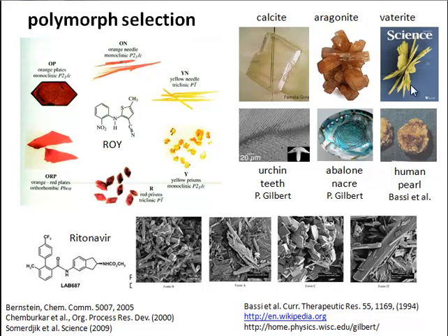These all have the same chemical composition, the same calcium carbonate structure at the molecular level, but it's packed differently into the crystal structures, and it gives you very different crystal morphologies and very different physical properties. Different organisms have learned to use these for different parts of their skeletons for all practical purposes. This one, by the way, is a human pearl, which has vaterite in it.